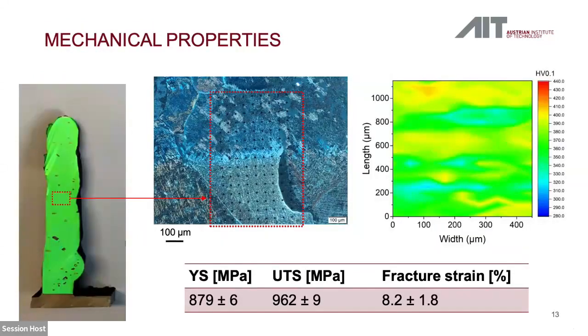Now we will come to some mechanical properties of the material. What is shown here is a hardness map that shows some variations. These variations range from about 300 HV to above 400. And this is simply a result of the strong orientation dependence of the material. The overall tensile properties are shown below here. We gain very good strength properties that are comparable to wrought material. The shortcoming is the fracture strain that is still slightly below 10%, but it can be improved by subsequent heat treatment.